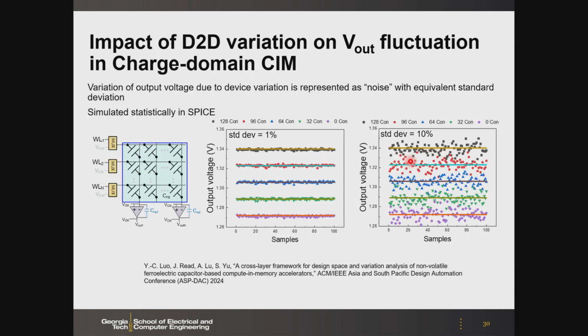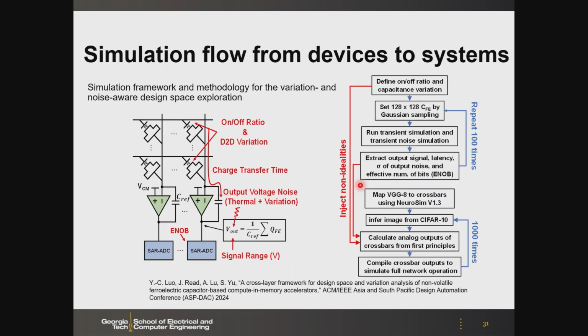So here, then the challenge, as I mentioned earlier, is the variation, right? Depending on the cell-to-cell variation and thermal noise, the output voltage may fluctuate. So that may cause some inference accuracy degradation at the system level. So we have to incorporate that into the inference accuracy estimation. That's why we set up this framework from devices to the system. We look at the impact of on-off ratio, device-to-device variation, the charge transfer time, and the thermal noise variation, and so on, to look at what is the inference accuracy if we use this technology, right?